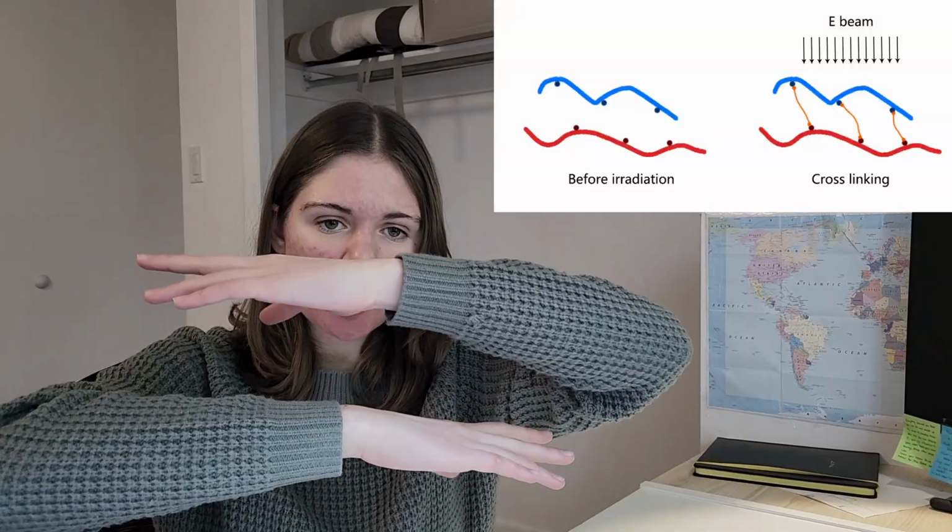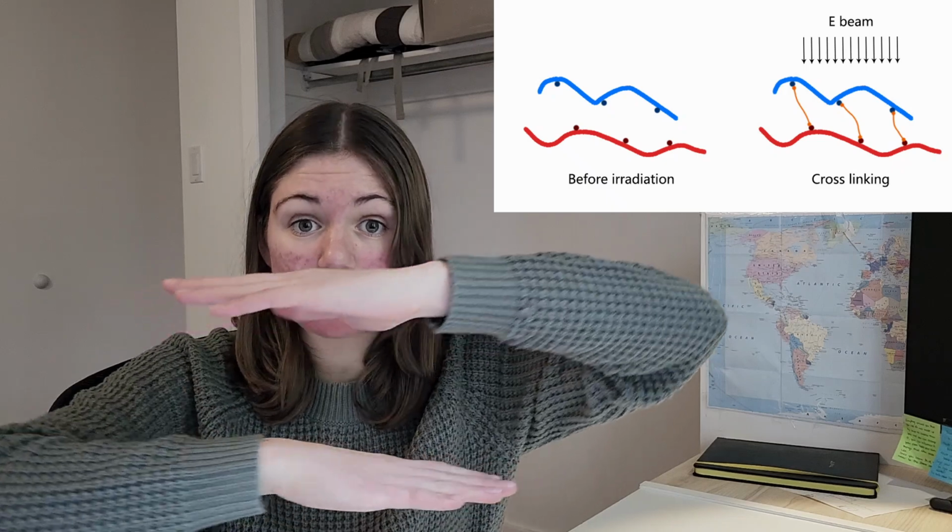One thing that they do is called cross-linking, which is like if you have two chains here, you add bonds between the two chains so they cannot slide like this. This does help with preventing crystallinity, and it also helps by increasing the mechanical stiffness, but it also increases the glass transition temperature, which we don't exactly want. So there's a bit of a vicious cycle here, and that's a prime example of what makes electrolytes so hard.